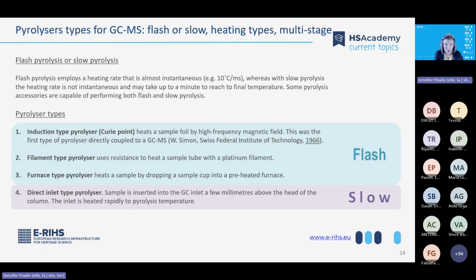Pyrolysis heating rates can be fast or slow. Flash pyrolysis is almost instantaneous. So we're talking about 10 degrees Celsius per millisecond, whereas a slow pyrolysis has a heating rate that may take up to a minute or two before reaching the final temperature. Some pyrolysers are capable of performing both flash and slow pyrolysis, and I'm going to show you 4 different types.